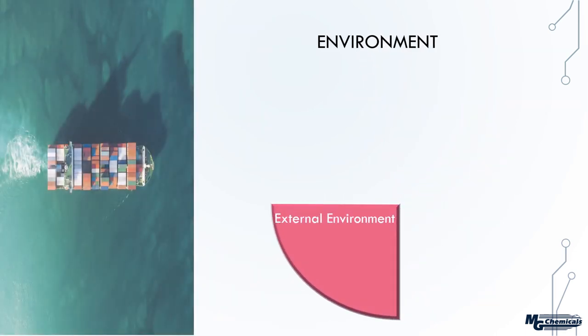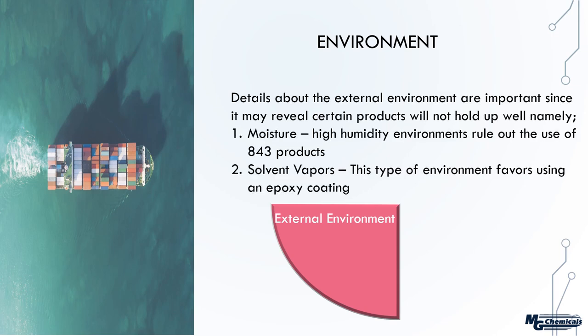Next, we want to look at the external environment. And with that, we want to look at two main things. One is how much moisture is present in the environment. So if it's a freighter out at sea with high salt water content, that basically rules out the use of the 843, the silver-coated copper. The reason is that over time, this moisture will corrode that product. And once it corrodes, it really starts to lose its conductivity and shielding performance.